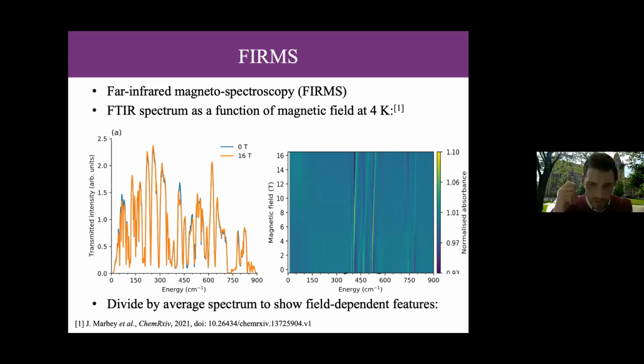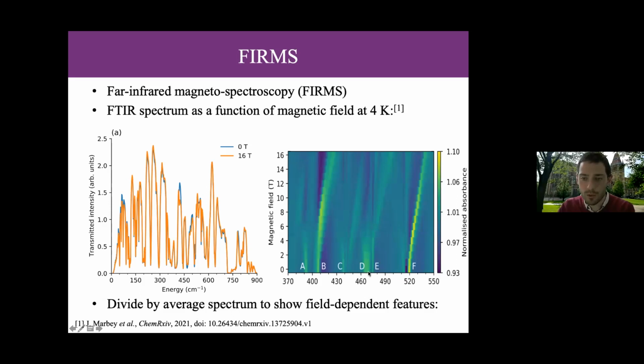So now your brain switches on to saying, hey, this looks a lot like Zeeman splitting, and that's exactly what we're trying to probe here. And you can zoom into this most feature-rich region around 450 wave numbers, which I do here, to show these really nice curves. And so these are states that are dependent on the magnetic field, and their energy is changing. And we are measuring that with an infrared spectrum. And so this is a FIRMS spectrum that we're going to try and understand.